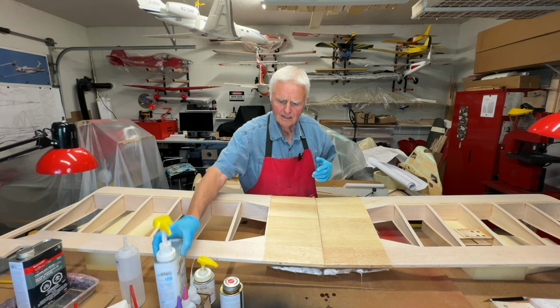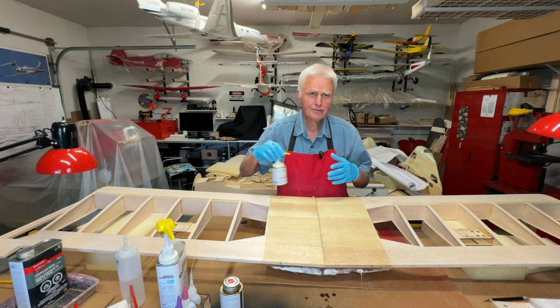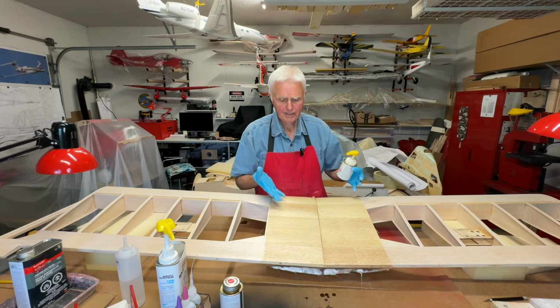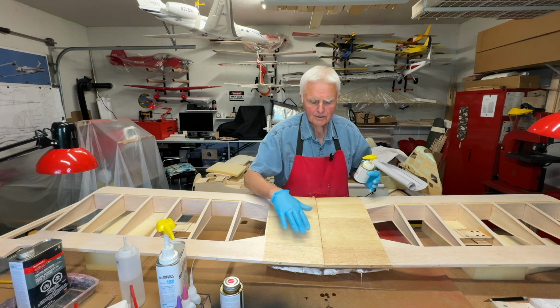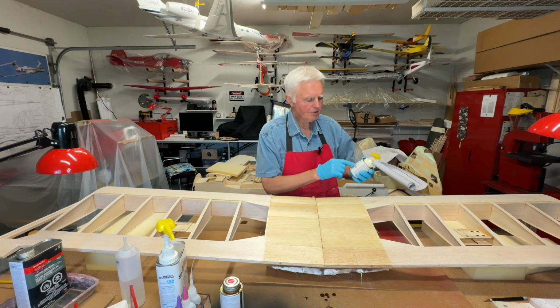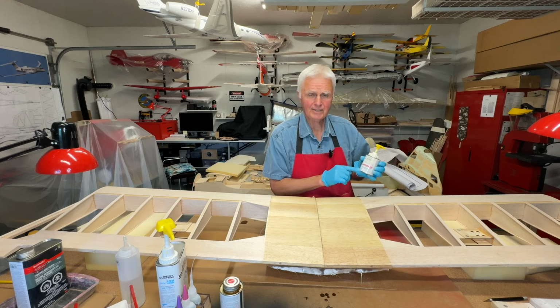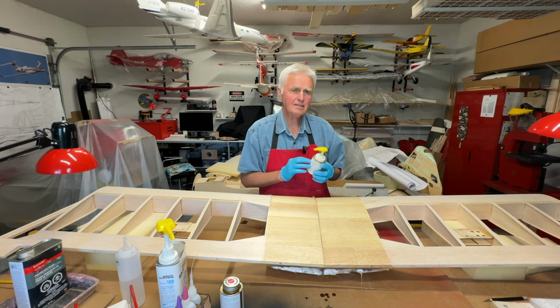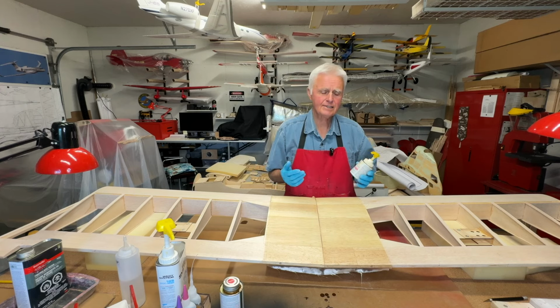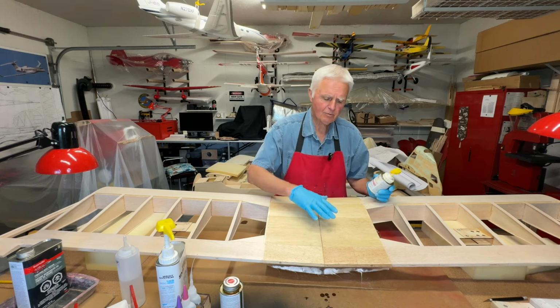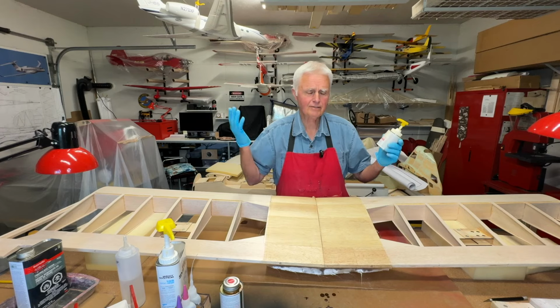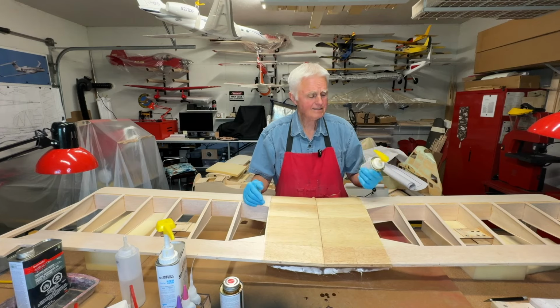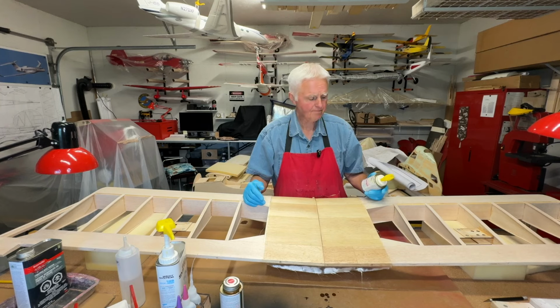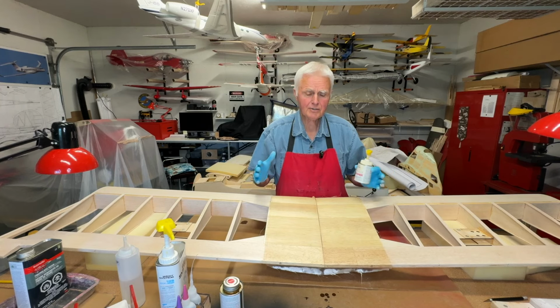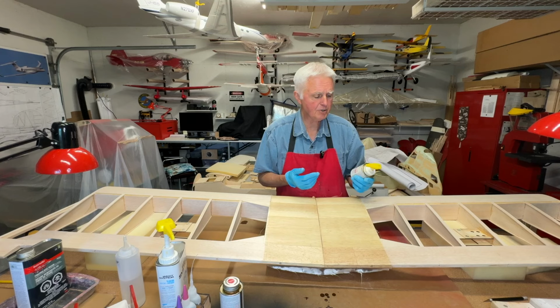It comes with different hardener formulas. For example, the one I used here, because I wanted a little more time to work with, is what they call the slow hardener, which is designated as 206. It has a pot life of about 20 to 25 minutes. But once you start applying it, you can easily work an hour with it. It takes 10 to 15 hours to cure. So I use that for bigger projects, just to afford me more time.